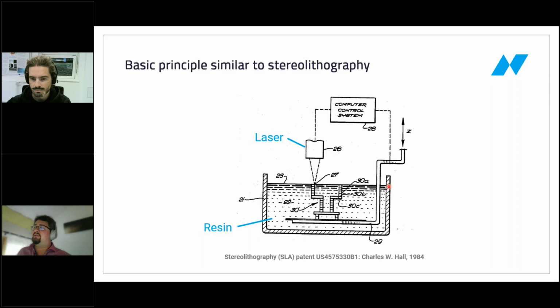And a common 3D printing technique is called stereolithography that was invented and patented in the 80s. And this is very similar to our technology. So I can use this to explain some of the basics. You have a laser in both technologies, and that laser shines onto a reservoir of UV polymerizable resin. And then the laser beam is moved to the different positions in a layer. And this is used then to cross-link and polymerize the resin in specific locations. And then you move by some method in a delta Z. And in the end, you have a polymer object that is basically built out of the cross-linked resin. And this is the same in both technologies, stereolithography and two-photon polymerization.